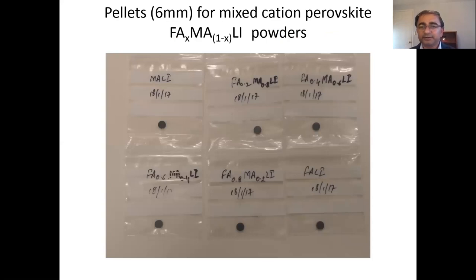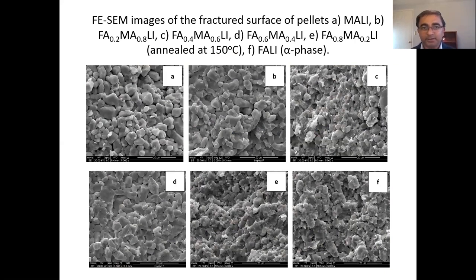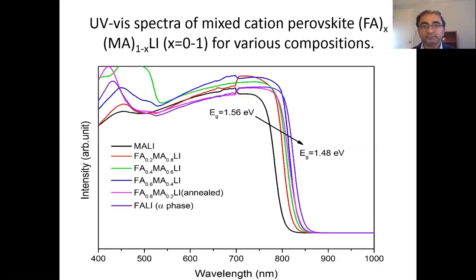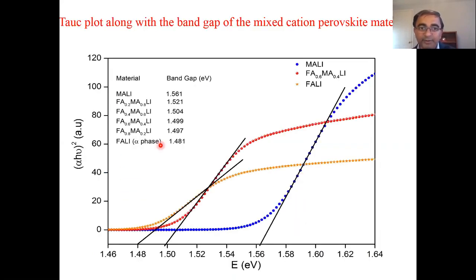I also made pellets of that for some conductivity measurement using impedance spectroscopy. These are some pellets, SEM, FESEM, and you can see all the grains are of similar sizes in all the materials. And I have done absorption spectra, and calculated the band gap of these materials. You can see from here the band gap ranges from 1.5 to 1.4, and this is very close to the optimum band gap required for solar cell materials.